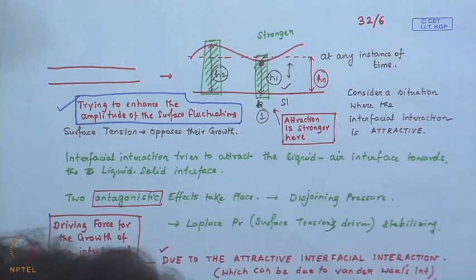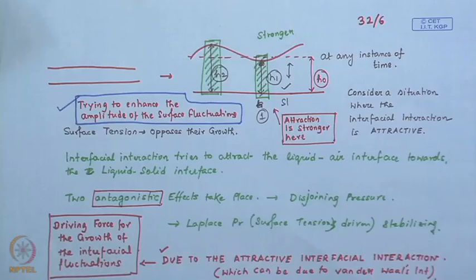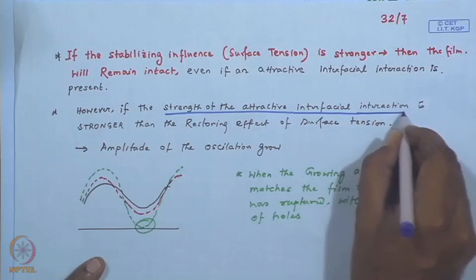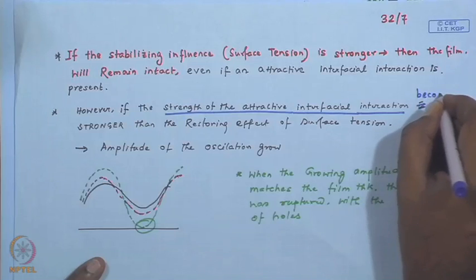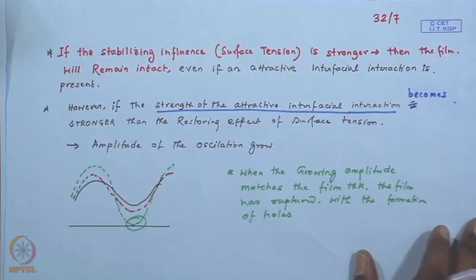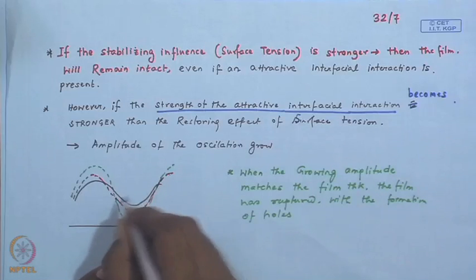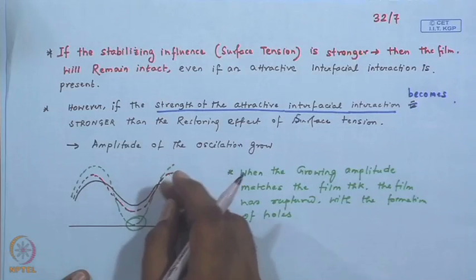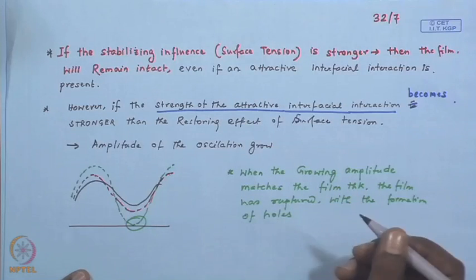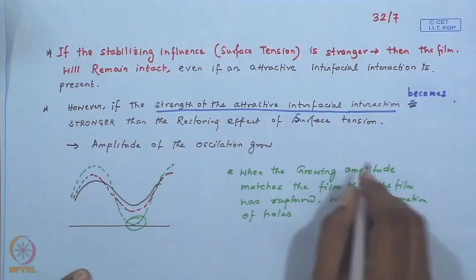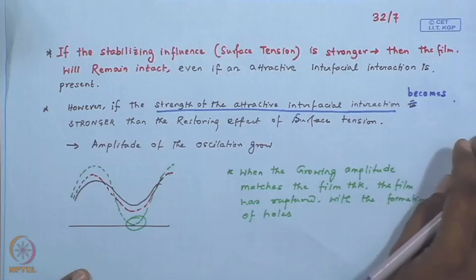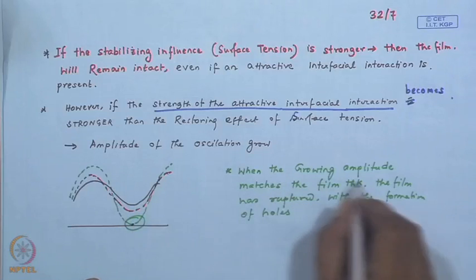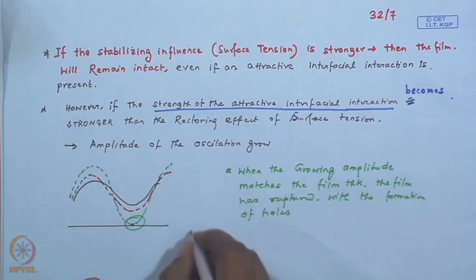And in the event that the strength of the attractive interfacial interaction becomes stronger than the restoring effect of surface tension, then eventually these tiny surface fluctuations grow in amplitude, and progressively their amplitude grows, and when the growing amplitude of the film matches the film thickness, the film has ruptured. What it means that the amplitude of the film matches the film thickness, essentially the two